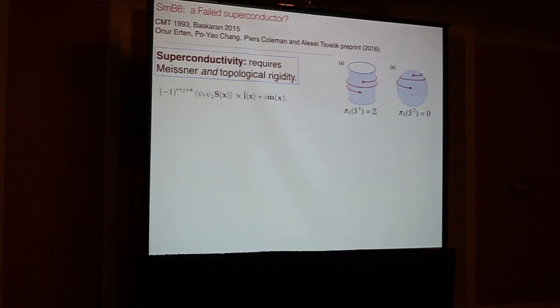So we've been playing with a model of samarium hexaboride, which involves a composite order parameter, a bound state between spins and pairs. And this composite order parameter is rather unique because it's triplet, but it has no orbital angular momentum. And so unlike conventional triplet order parameters or higher angular momentum pair states, it doesn't lock to the lattice because it doesn't have the orbital component.